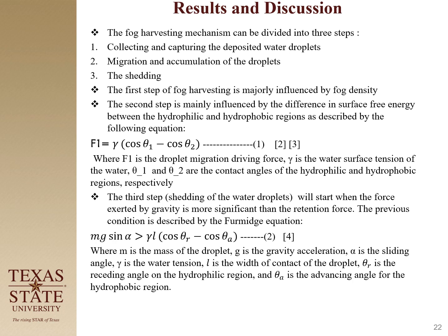For the migration and accumulation, the hybrid is better because the force that drives the droplet to move from the superhydrophobic into the hydrophilic is shown in equation 1. So the difference between those surface energies, and thus the contact angle between the two, makes the droplet move over there, and then they will grow until their size makes gravity stronger than the capillary pinning force that attaches them to the surface, and shedding will happen.